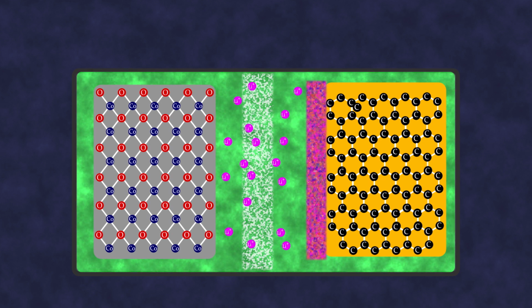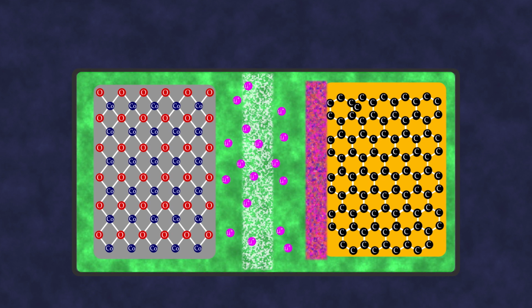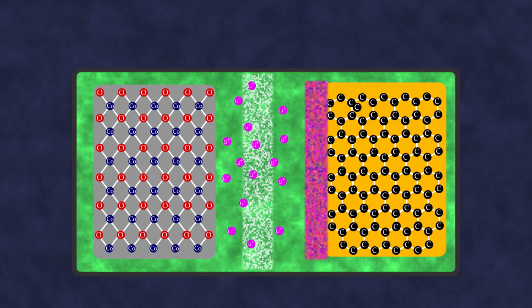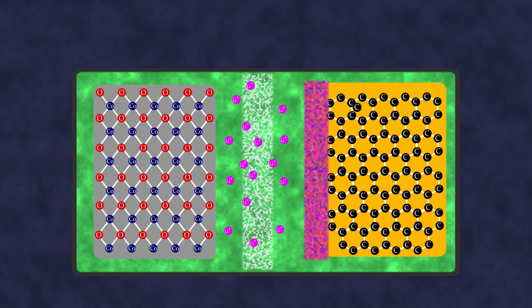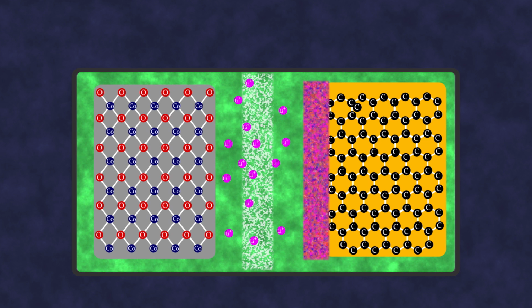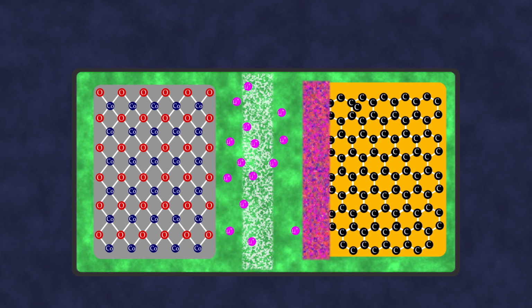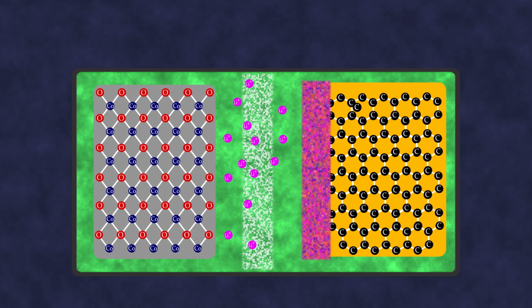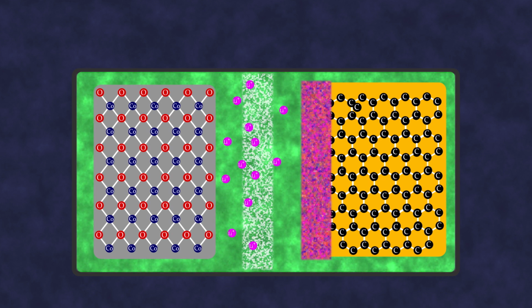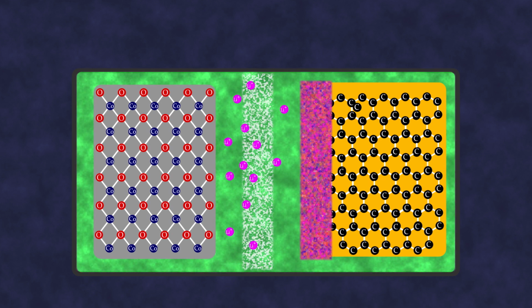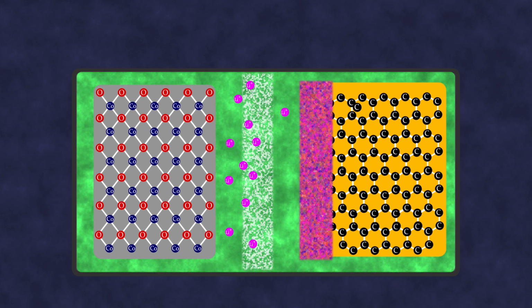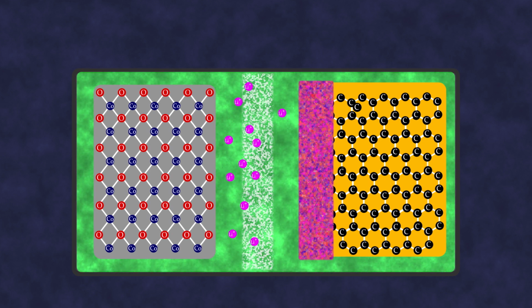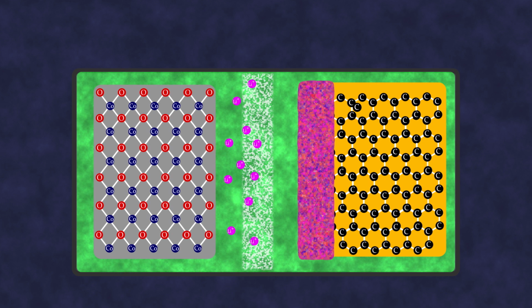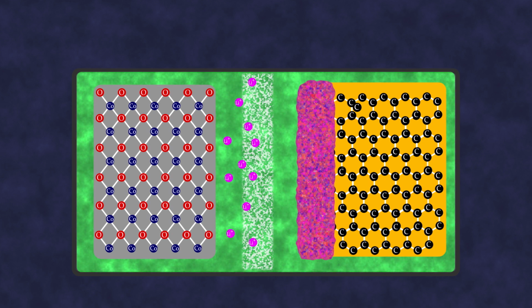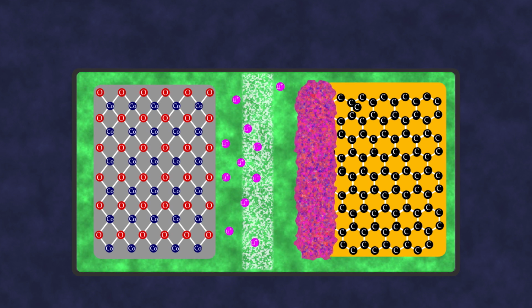This layer thickens and becomes denser as the battery operates. This leads, firstly, to a reduction in the concentration of free lithium ions, and secondly, it becomes more difficult for the remaining free lithium ions to pass through the layer, increasing the battery's internal resistance. This, in turn, reduces the battery's efficiency and causes it to heat up more during operation, further increasing resistance. Worse still, the solid electrolyte layer may grow unevenly, damaging the graphite layer, which also reduces capacity.